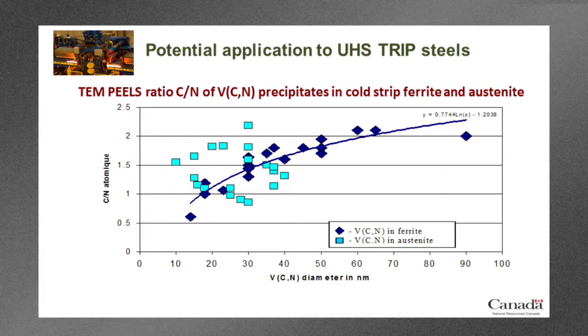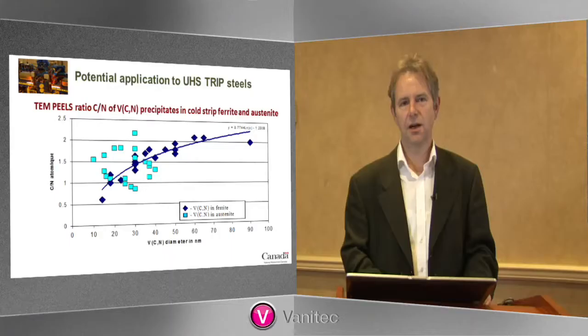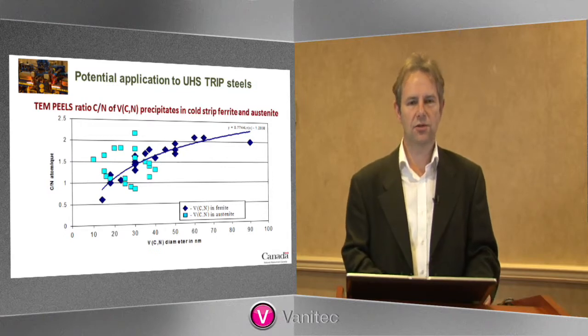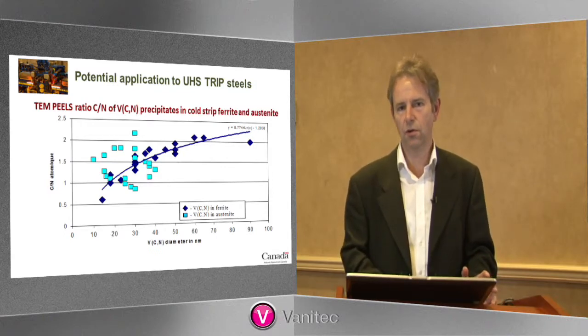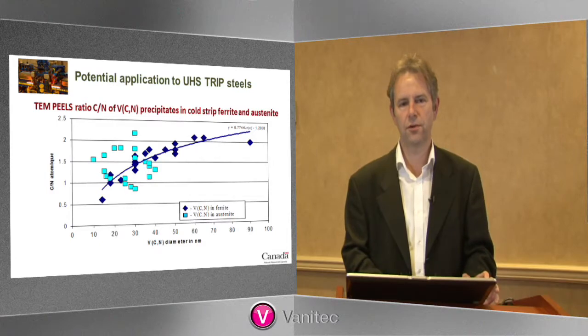And there are two different colors of points in here. There are the very light blue points, which are precipitates that we measured in the austenite phase, and the dark blue points are precipitates that we measured in the ferrite phase. And what you can see, first of all, in the austenite phase is there's no relationship between the size of the precipitate and its carbon to nitrogen ratio, its composition. It seems to be quite random. Whereas in the ferrite phase, it's completely different. The smallest precipitates are always very rich in nitrogen, and the biggest precipitates are rich in carbon. That is a very strong indication that what we have here is actually growth and coarsening in the ferrite phase, and in the austenite phase we don't have anything at all like that, so no growth or coarsening in that phase.